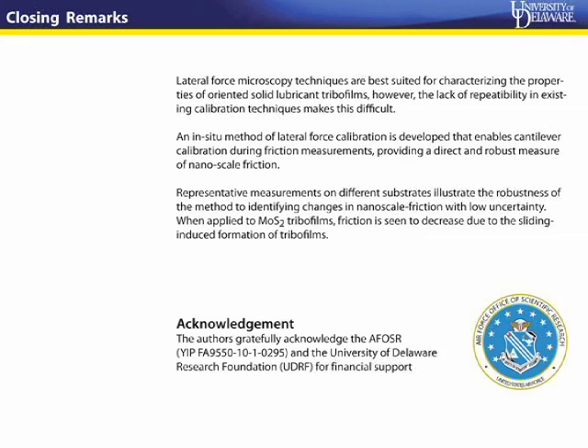One of the things that my research looks at is MoS2. Doing nanotribological measurements on MoS2, in the last slide that I showed, we're comparing the different parts of the MoS2 coating, what happens when you slide on it, and how you quantify the properties of tribofilms. That really is the focus of my research, trying to characterize the tribological and mechanical properties of these very thin tribofilms. And so, in lateral force microscopy, we saw a need for a more robust method of doing friction measurements at that scale, and that's how this research came about.